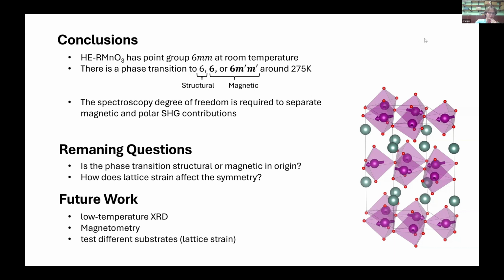And the structural transition to 6 is not something that has been reported in these manganites before, to my knowledge. It could be a result of the high entropy formulation. It could also be something exclusive to thin films because most of the literature is on single crystals.